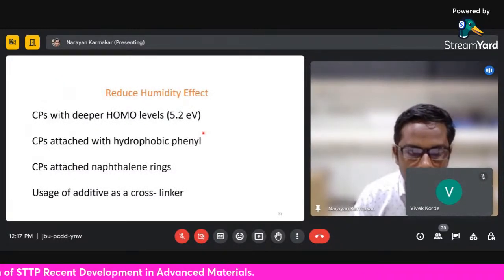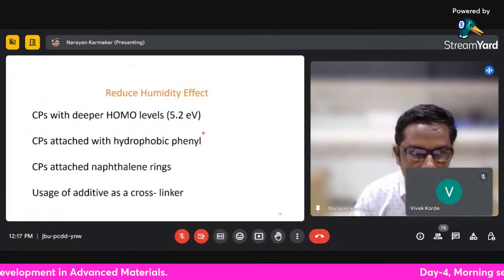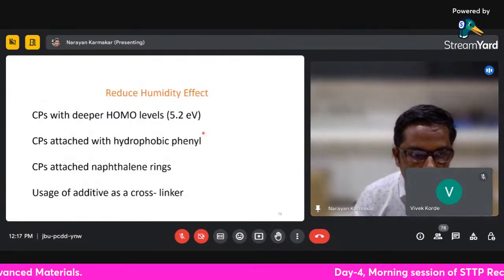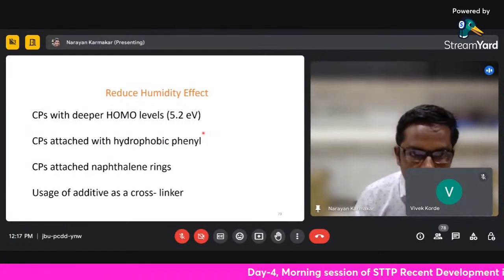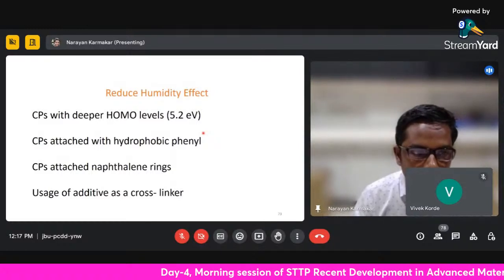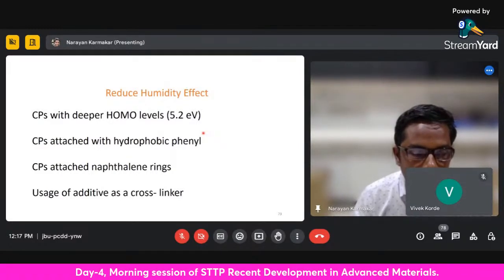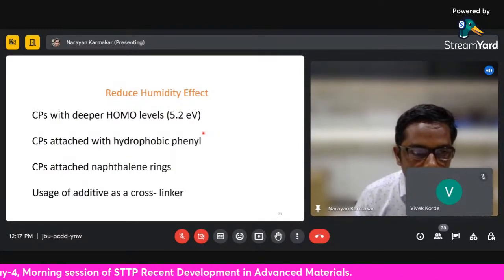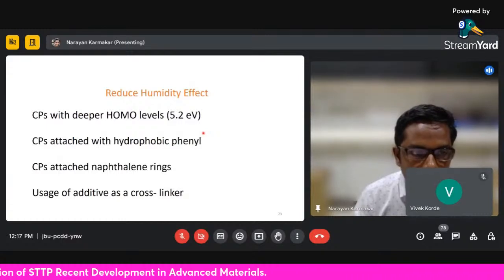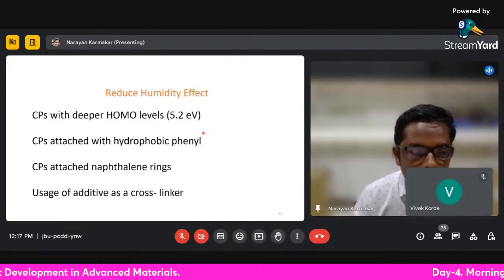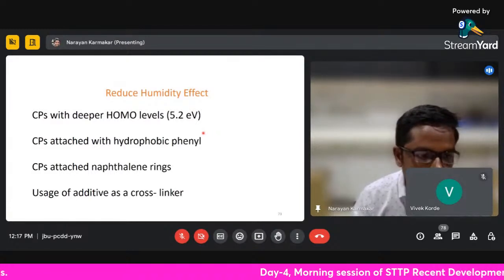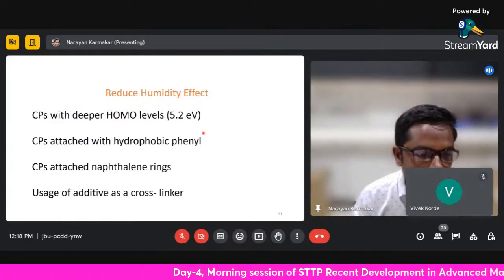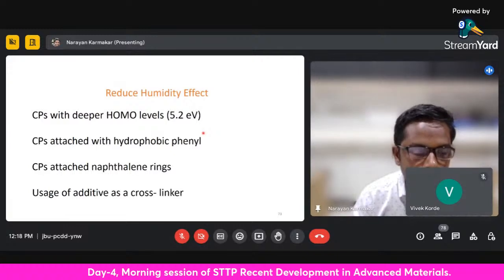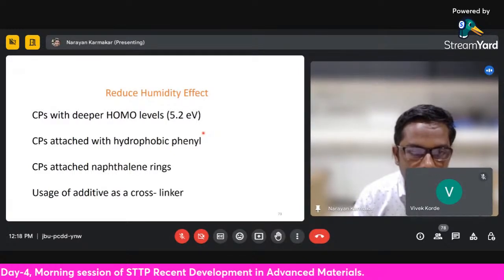To overcome this humidity problem, what we do is use conducting polymers with deeper HOMO levels, about 5.2 eV. We can functionalize this conducting polymer using hydrophobic phenyl or naphthalene rings, and improve the effect from humidity. We can also make use of additives like cross-linkers to reduce the humidity effect of the gas sensor.